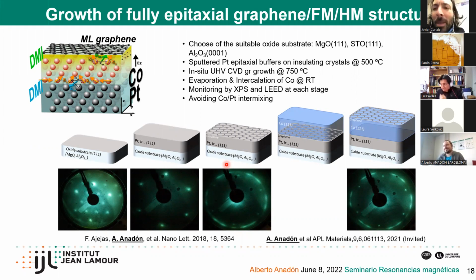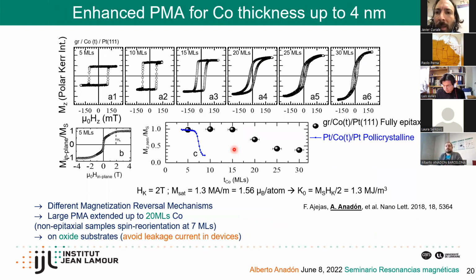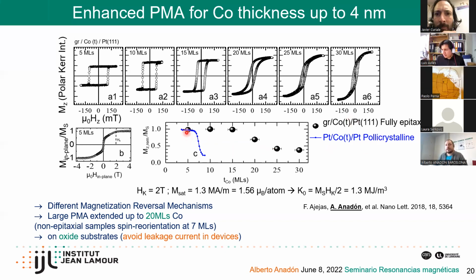Very nice talk. I have a question regarding this sample. In slide number 20, I guess, you show the threshold for the PMA shift on that graph. Are you sure that the change is due to the graphene or due to the crystallinity of the cobalt layer? Can you say something about that? Even if you grow epitaxial cobalt in these kinds of systems, I don't think you will get much higher than this reorientation transition.